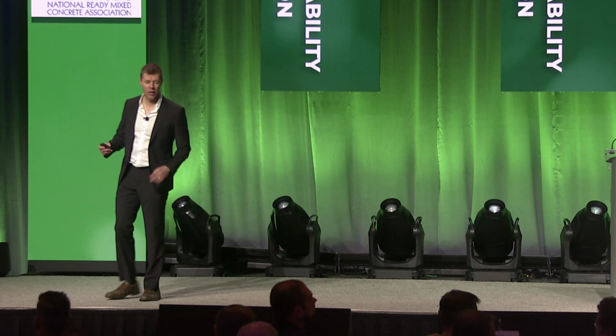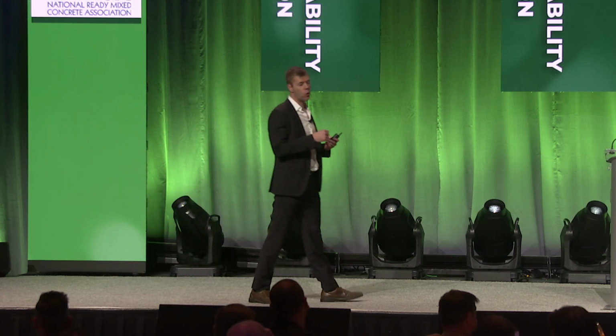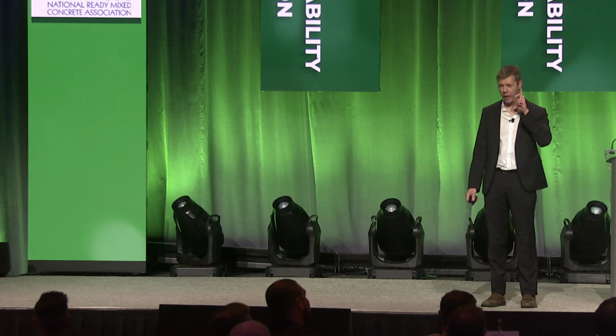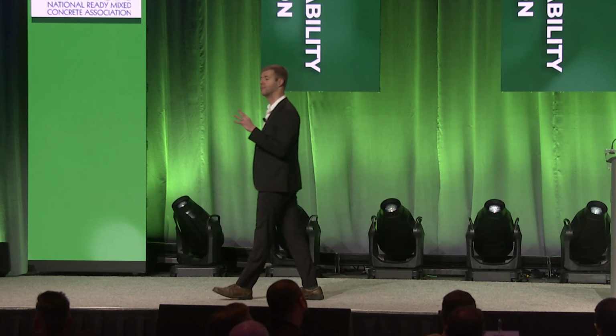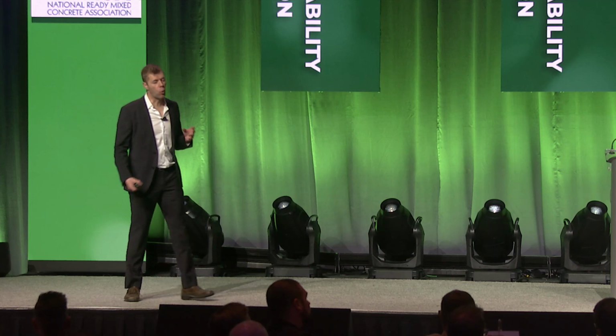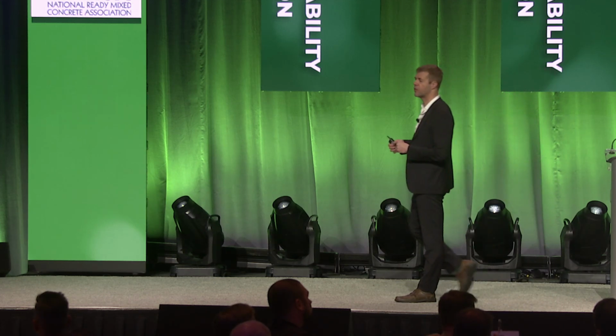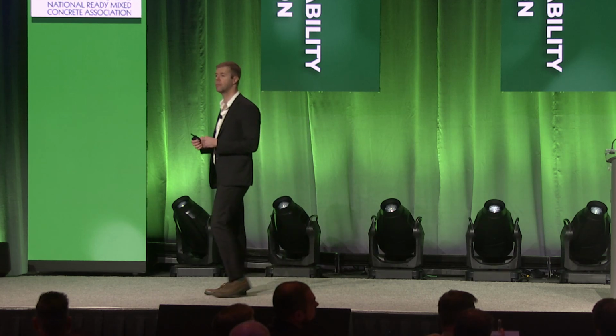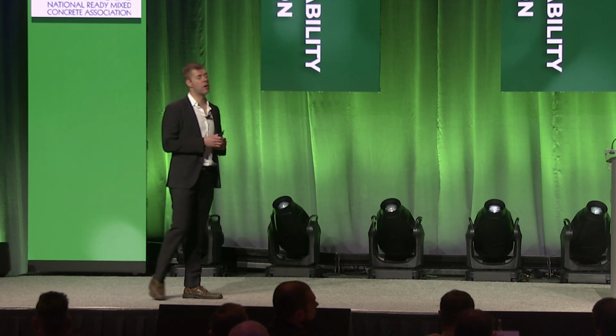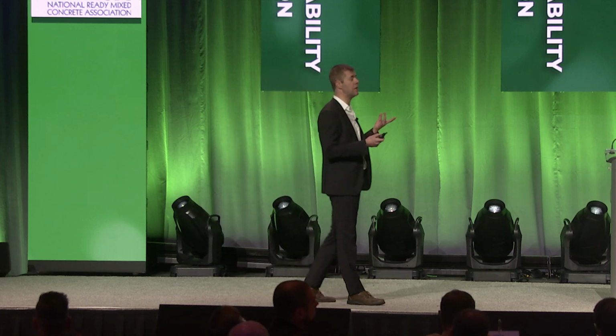Okay? When concrete cylinders don't reach the specified strength, the ready-mix producer is blamed for the mix not being right. That's what happens, in my experience. And we need a way to address this. We really, really do. But what if we could measure the water-to-cement ratio in fresh concrete? What if you could show that the concrete meets the specification as it leaves the plant? What a way to protect yourself. We would measure what matters, because really water-cement ratio is the key thing. I'll talk about that in just a second. I'd place less of an emphasis on strength and slump specifications, which I think is huge.